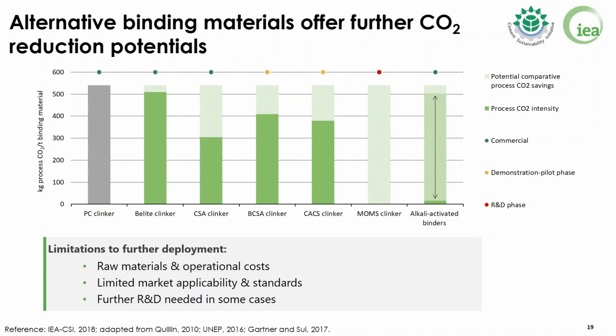As you can see from the graph, there are materials like the so-called MOMs, where MOMs stands for magnesium oxide derived from magnesium silicates, and due to the fact that this material absorbs CO2 during curing, it can almost offset completely its CO2 emissions. However, there is a limitation for its deployment that is linked to the availability of raw materials and operational costs for the treatment and the preparation of material.